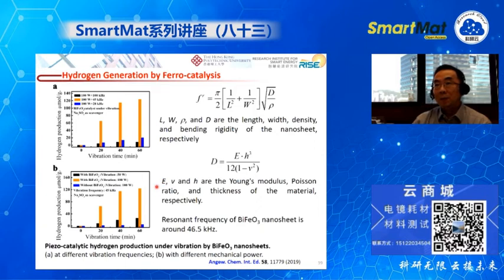But when we apply an ultrasonic wave to the material, we do find some hydrogen production. And we also found that the hydrogen production is more significant when the ultrasonic frequency is around 45 kilohertz. And that frequency is very close to the resonance frequency of our nanosheet. We do some detailed calculation to find the resonance frequency of the nanosheet, and we found these two frequencies are really very close. So this is also a proof of the piezocatalytic effect.